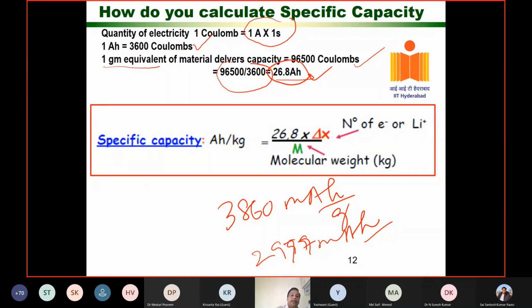So specific capacity I can write in terms of 26.8 divided by molecular weight into the number of electron transport during electrochemical process. Basically, this is theoretically. In real, in practical, you don't get all the lithium or all the lead, like 1 electron transfer or 2 electron transfer or 3 electron transfer in case of aluminum. So the amount of electron transport into 26.8 divided by the molecular weight will give you specific capacity. This is how we calculate.